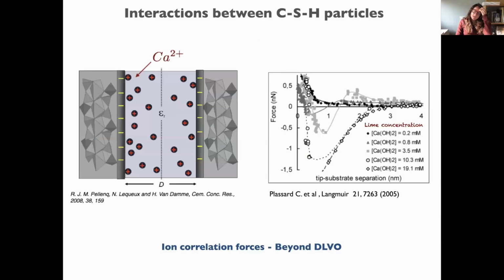So if we try to understand the region of cohesion between the CSH particles, we go down to the experiments that Roland explained with the atomic force microscope. The key finding there was that it depends a lot on the concentration of calcium ions in the solution. If we try to put this in the framework of electrostatics, we see on the left that CSH particles can be represented by two charged planes with a high surface charge. In between, we have the electrolyte with different types of ions, but the most dominant ion is calcium, which is divalent.